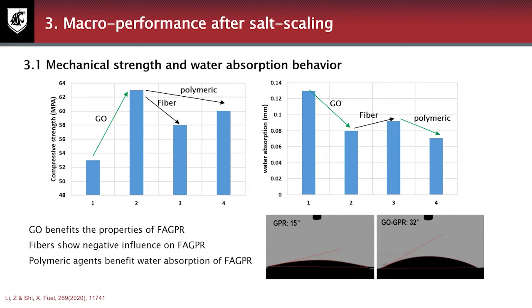And the positive influence induced by graphene oxide, we have tested and summarized many mechanisms in our publication, and the main reason is that geopolymer makes the microstructure denser and then increases the water contact angle to keep the water out.